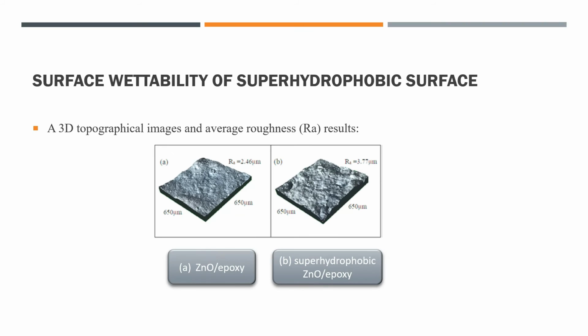Next, the study was carried out on the surface wettability of the superhydrophobic surface, a 3D topographical image, and average roughness results. A is the zinc oxide and epoxy. B is the superhydrophobic zinc oxide and epoxy. Laser scanning confocal microscopy was used to analyze the average surface roughness and 3D profile of the coated samples. Laser scanning confocal microscopy topography images of the surface of zinc oxide and epoxy and superhydrophobic zinc oxide and epoxy coatings were shown, together with average roughness findings.